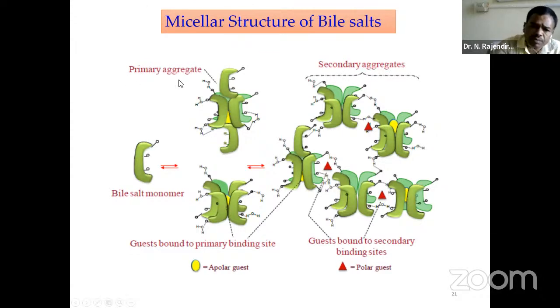So this forms two different types of micelles, that is, the primary micelles and the secondary micelles, where the primary micelle is driven by hydrophobic interactions, whereas the secondary micelle is formed by hydrogen bonding. So after the formation of micelles, we can use this material as a template for the preparation of metal nanoparticles.